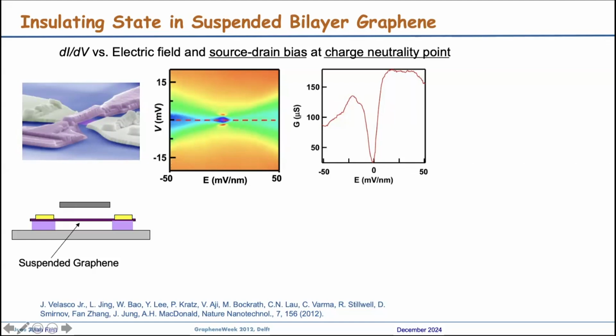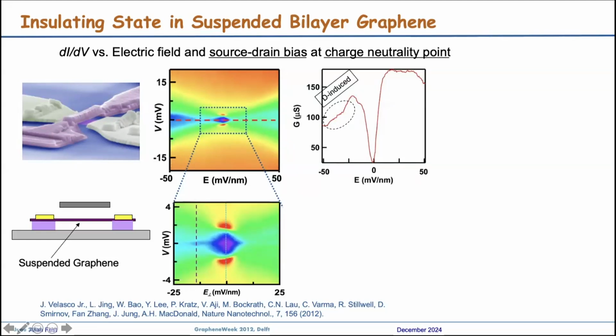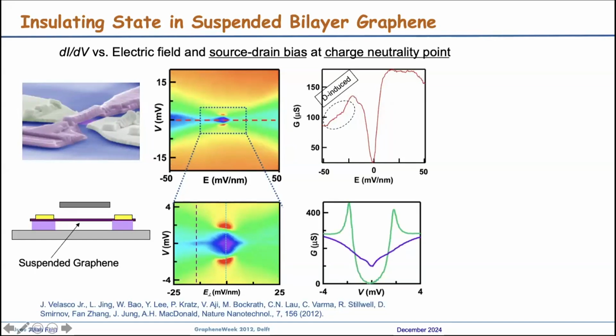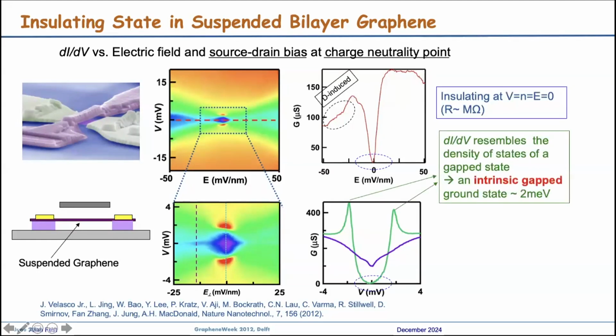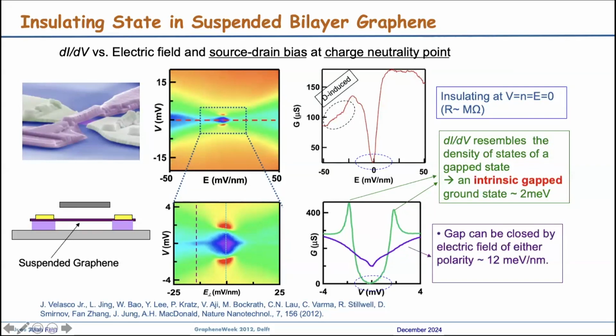So this blue region is very low conductance. Take a line trace here. We have close to 0, this is like megaohms. And then at large electric field, the conductance first increases and then decreases again. If we do a vertical line cut, for example at the charge neutrality point and zero electric field, the conductance versus bias looks like a spectroscopy measurement of a gap state with sharp peaks. So what we conclude from this is that it looks like the density of states of a gap state. This is an intrinsic gap state of 2 meV, and this gap can be closed by electric field of either polarity.